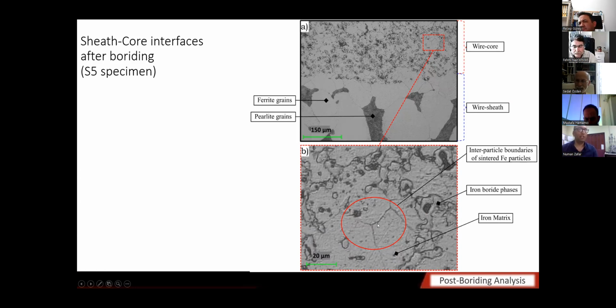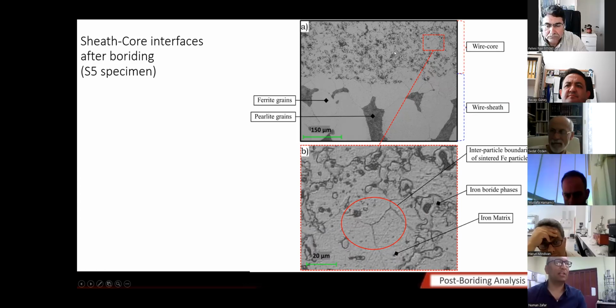inter-iron particle region, in which there was no B4C particle to serve as a boron host. So they don't have any iron boride phases formed here. But in all other regions at which iron particles were in contact with the B4C particles, iron boride phases have formed.